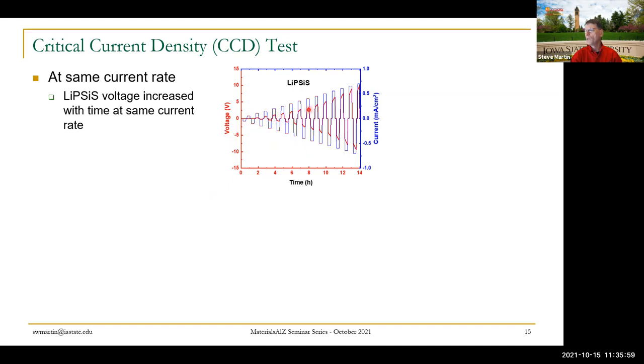The red is the voltage. If you look real carefully, you can see the red's the voltage, and the blue is the responding current. Now, these are galvanostatic measurements. We apply whatever voltage is necessary to get a responding current. And you can see the current plateaus are constant. They're growing because we purposely want to keep going until we destroy the glass, as it were, until we break down the glass. But it's the voltage, you see, that's growing. And now if Ohm's law held, these flat current plots would be associated with flat voltage plots. And that's not what happens. See, there's some structure.